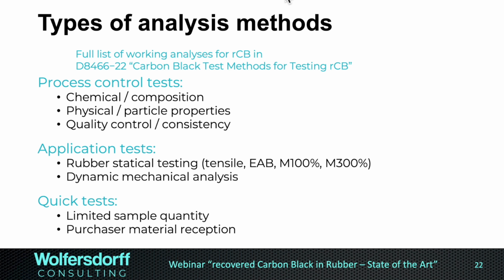Application tests, of course, are in rubber-specific applications, or if you look at plastic, which this webinar is not about, we need to test color and other things. And so we have the rubber static testing, which would be the tensile strength, the elongation at break, the modulus 100, modulus 300. For the tire, of course, because we have a frequency in the load, we need the dynamic mechanical analysis. We get more into details of that in a moment.